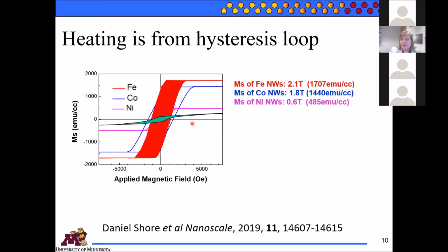The reason that we're concerned with that is if you take a look at what's, oops, I didn't know if I had the label there. These are the iron oxide particles that are being used in nanowarming right now. First off, you'll see that the area is much smaller, which you'd expect, even just because they're officially superparamagnetic. But at high frequencies, the hysteresis loop opens up and gives you some area, which gives you some heating. But we know the MS of iron oxide is less than these different metals. And also because it's superparamagnetic, but then at a high frequency you have a hysteresis loop, it opens out to a very high field. So you can see there's still area to the loop. It's not fully saturated, even pretty high out, like 5,000 Oersted.